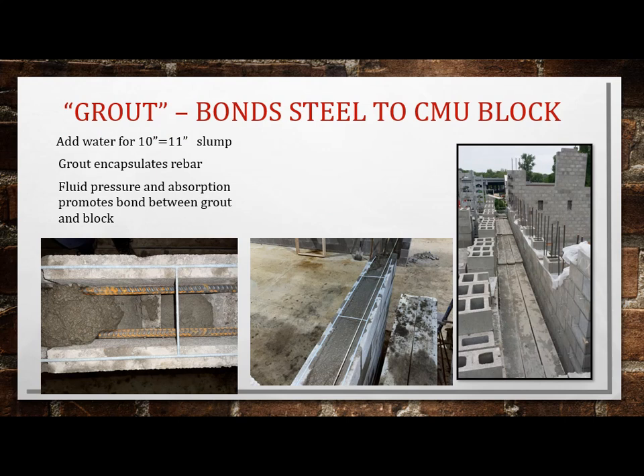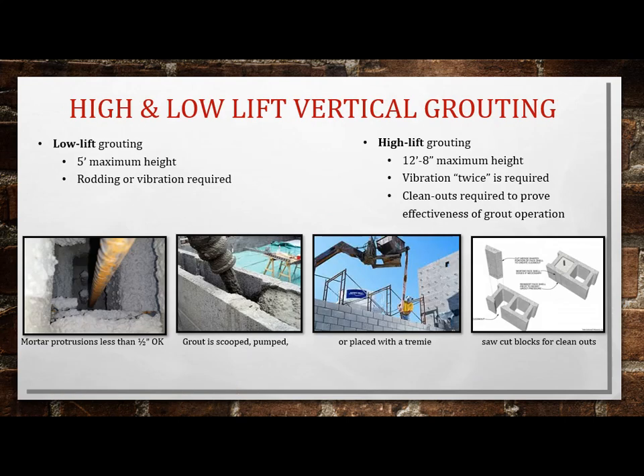It's actually created by the fluid pressures and the absorption, like little cementitious tentacles of the grout actually entering the microscopic pores of the CMU block. It's kind of like a weld that has good bond strength, and that's necessary. So it creates a composite material similar to reinforced concrete. You've got block, grout, and rebar. That's just one. There are 2 techniques for grouting.